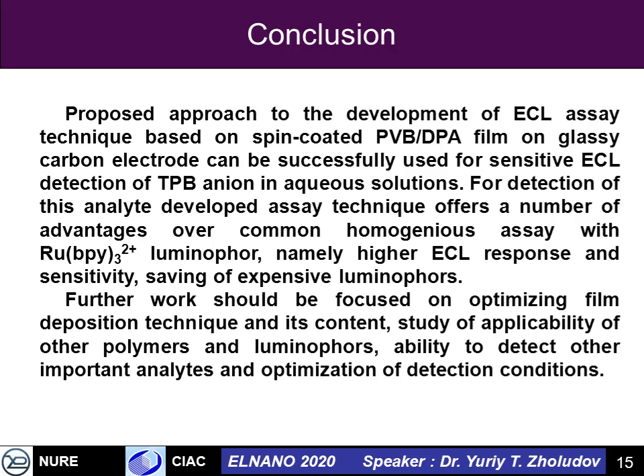So it is possible to conclude that, first of all, the home-designed spin coating system, which can be made very simply and cheaply, is working well. It allows depositing very nice spin coated films. And second, those spin coated films consisting of polymer with a fluorophore like diphenylanthracene, a polycyclic aromatic hydrocarbon, give very efficient ECL emission in aqueous solutions and can work for detection of coreactants like TPB, and potentially some other coreactants can be used.